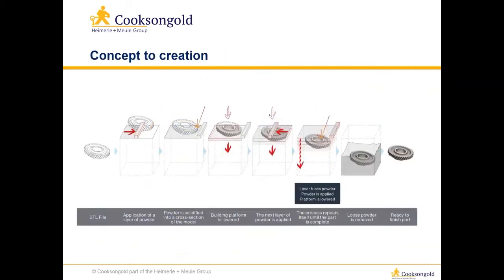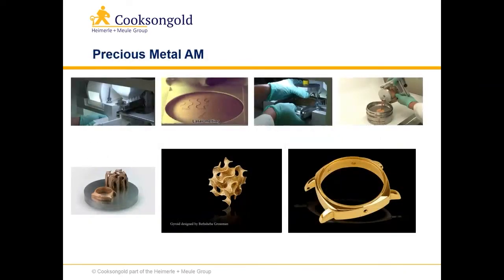So very, very quickly, how the technology works. We haven't got any videos today because they don't particularly work well on Microsoft Teams type webinars, but we're taking powdered metal, which we create here in the UK, and we're laying it onto a build platform and then printing the item slice by slice, 20 micron slices, which have a very, very fine microstructure, and so we don't suffer from orange peel in the same way that you could from traditional wrought processing techniques. So a layer of powder goes down, that slice of the geometry is melted, the next layer of powder is laid on top of the previous layer, and then that layer is melted onto that previous layer, and the part is slowly built up in a vertical way, resulting in a finished piece at the end. So these are some pictures from some of the videos which we normally run.